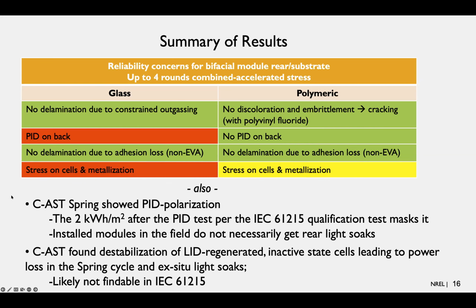So we additionally found that the combined accelerated stress testing spring sequence showed PID polarization. This was in the glass substrate with ethylene vinyl acetate encapsulant, the type that is susceptible to PID polarization. But in terms of the standards, the 2 kilowatt hours per meter squared that IEC 61215 has in it would mask that polarization. And installed modules in the field do not necessarily get 2 kilowatt hours per meter squared of UV dose. So bottom line is that bifacial PERC cells with glass backsheet and ethylene vinyl acetate encapsulant can show PID polarization, and it isn't an artifact. It could happen in real life.